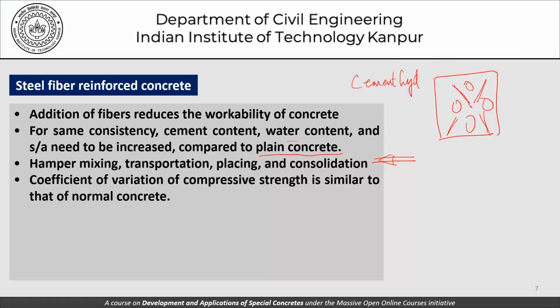And therefore, there is no reason to expect any change in the compressive strength or the variation in the compressive strength on account of fiber addition, except in a situation where we do not pay enough attention to the fiber addition issue in mixing, transportation, and placing, in which case the real culprit for observed changes in the compressive strength or its variation is our lack of attention to the mixing, transportation, placing issues rather than the fiber addition itself. So that's something which is very subtle and you must keep in mind all the time.